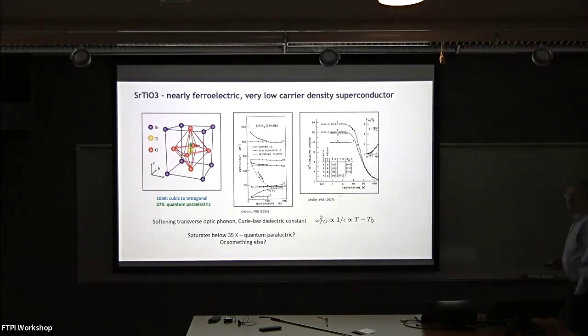And it has some instabilities. As you cool it down, at high temperatures it is cubic. When you get to 105 Kelvin, it goes in a small deformation from cubic to tetragonal. I'm in general going to ignore that. And the one which is of interest is that the titanium atom has a tendency to go off center. How do you know that?